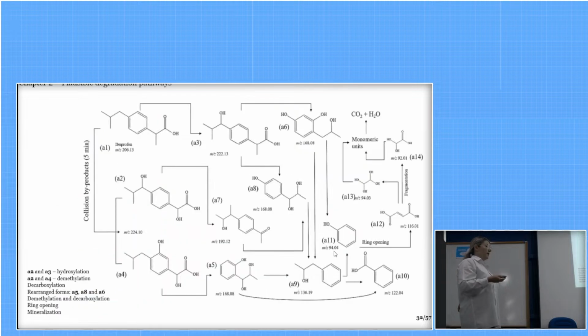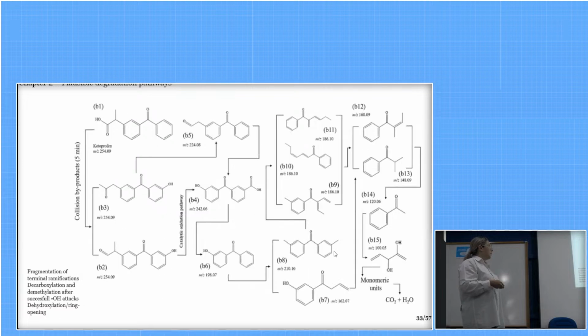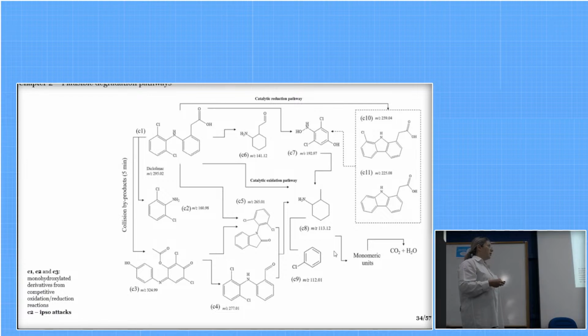Then we also investigated the degradation pathways for the pharmaceuticals studied, because this can point to possible mechanisms occurring by the catalyst. So here we observed sequential hydroxylation consistent with the formation of hydroxyl radical. For ketoprofen, the same process as ibuprofen occurred at slower rates, and for diclofenac, we were able to confirm the formation of 2 reductive fragments, which corroborates other possible pathways.